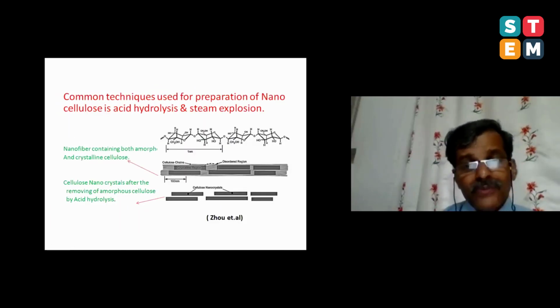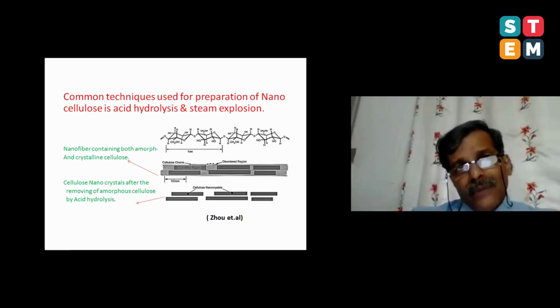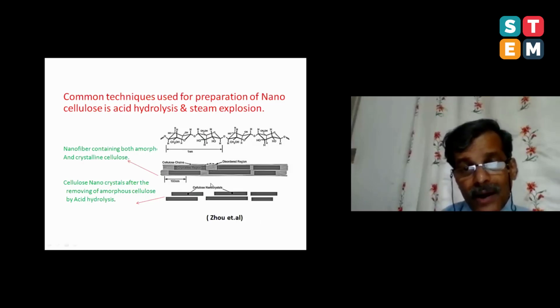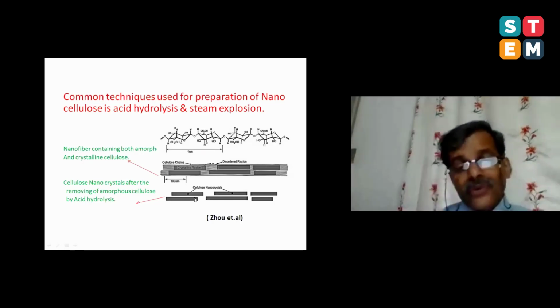I wanted to show you some nice work of Zhou and group. If you use a light acid for hydrolysis, acid hydrolysis with steam explosion process, you can get long nanofibers. Look at these long nanofibers. If you use a strong acid, you can kill all these amorphous regions. These are amorphous. This is crystalline. So in nanocellulose, you can see amorphous and crystalline parts coexist. And if you kill all the amorphous part using a very strong acid, you get small nanocrystals. Look, these are all short nanocrystals.